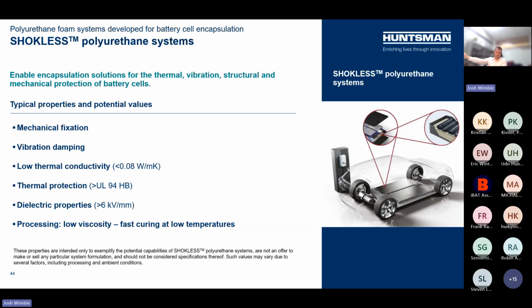The cure continues over days, as it does with all polyurethanes, but the workable time for potting a battery pack is typically 20 minutes. And that's great cure times, considering that these battery packs basically act as a heat sink. So when you're pouring in a material that typically reacts faster and better with heat, all that metal in the pack is pulling away from it.